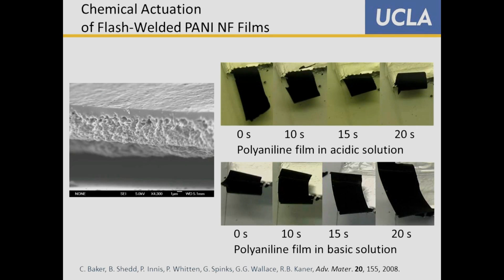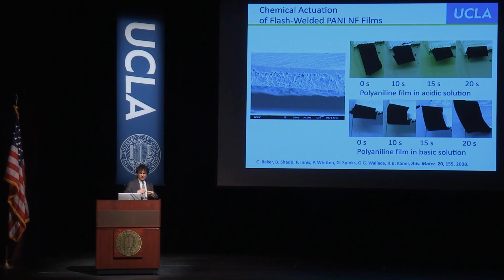I had the opportunity to spend a sabbatical in Australia with Gordon Wallace on a Fulbright fellowship. And what we did is we took this material and we simply melted the top surface. So this is looking at a cross-section. So you can see here's the nano part, here's the melted part. And we use this for an actuator. So we dip this in acid. The nano part absorbs the acid and expands. The melted part cannot expand.